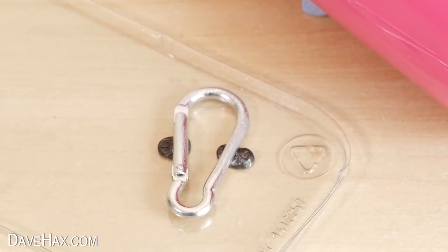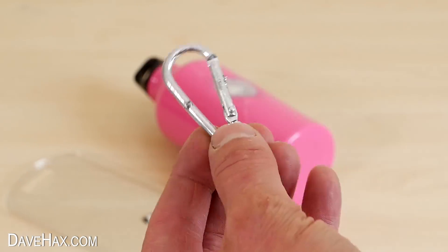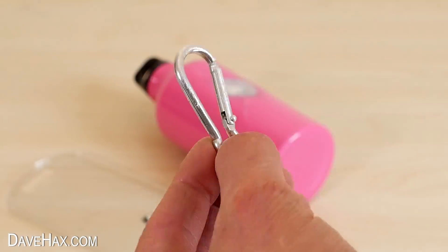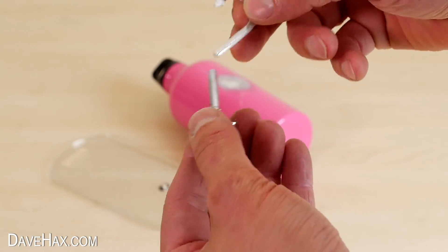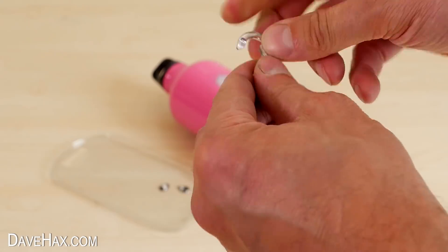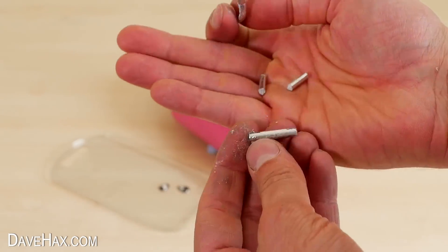After about half an hour there appears to be a crack in the paintwork running down the flask. The carabiner looks relatively unchanged so I picked it up, wiped off the gallium residue and tried breaking it with my hands. It just snapped clean in half — it became really weak and brittle and easy to break.